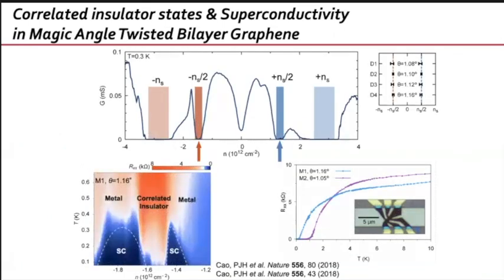So what happens is that we can tune, with an electrostatic gate, the number of electrons in our system continuously. If you tune to a given number of electrons or holes per Moiré unit cell, you can find various correlated states, including correlated insulators. And if you dope a little bit away from them, you can actually find electrically tunable superconductivity. And that's what happened a few years ago in my group.